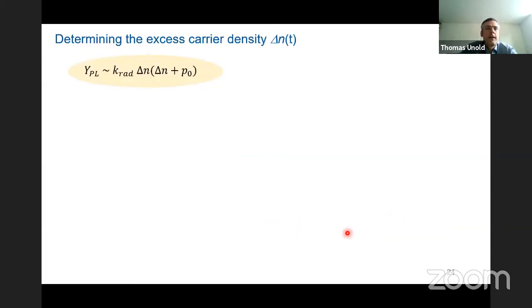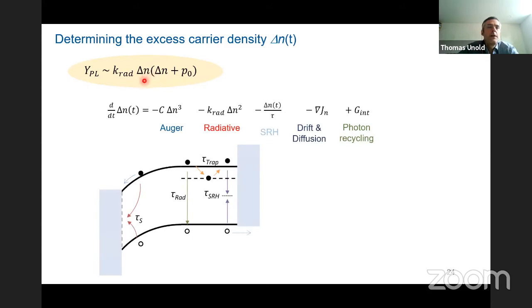So first, again, I think this was mentioned in talks already. The photoluminescence is basically given by the radiative recombination constant times the carrier density. This is a more general equation that includes high and low injection. What you need to know is this delta N, and the delta N is covered by this differential equation. It includes different recombination terms: Auger recombination, which goes by the cube, radiative recombination, which goes by the square, and then the Shockley-Read-Hall recombination. You can have drift and diffusion, and you can also have photon recycling. Very often the Shockley-Read-Hall term dominates, but not necessarily.